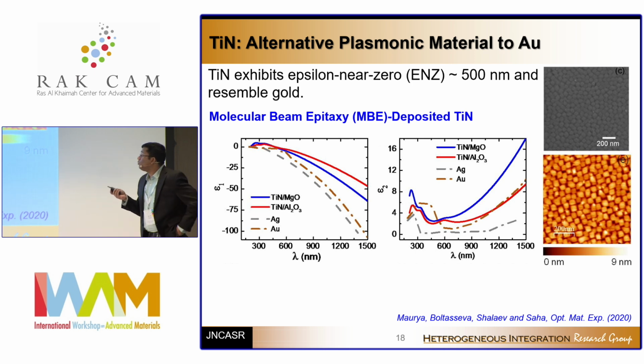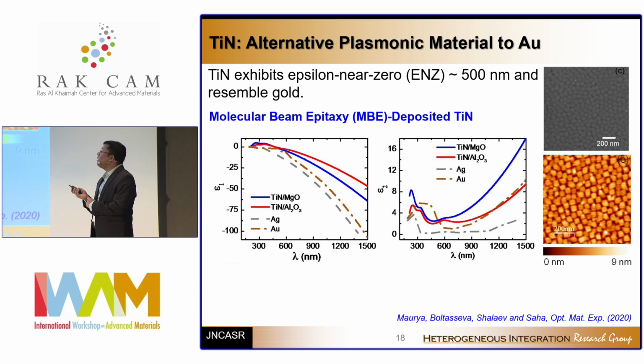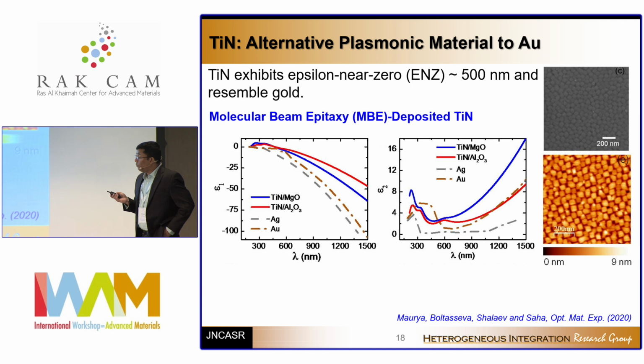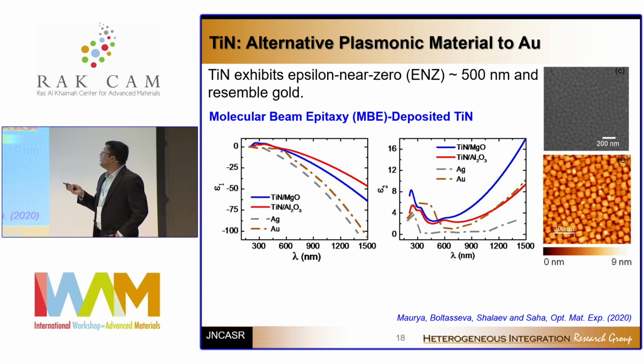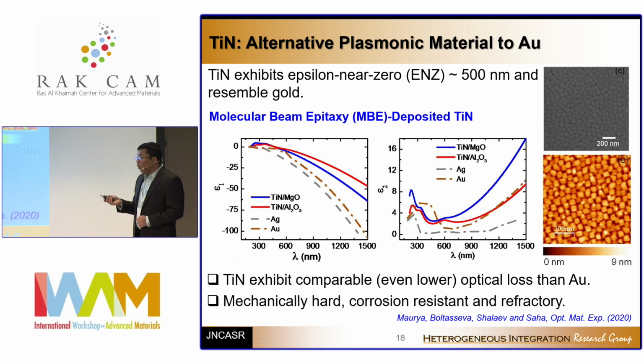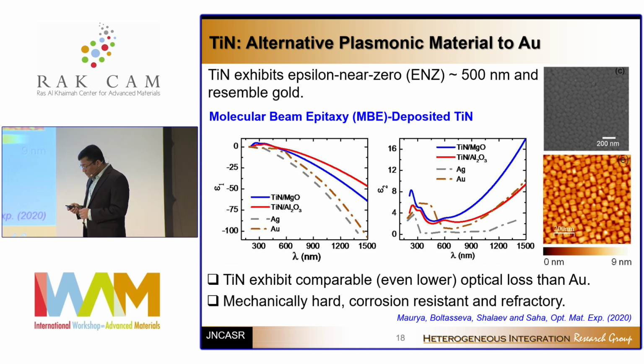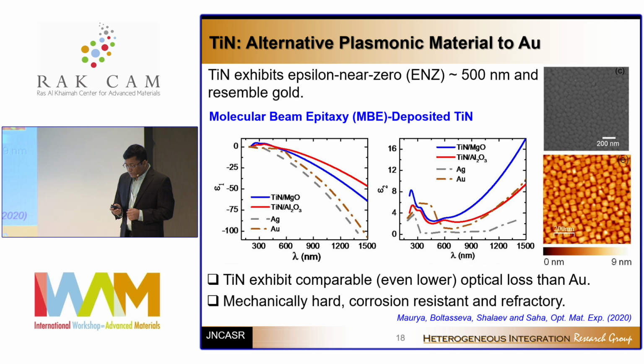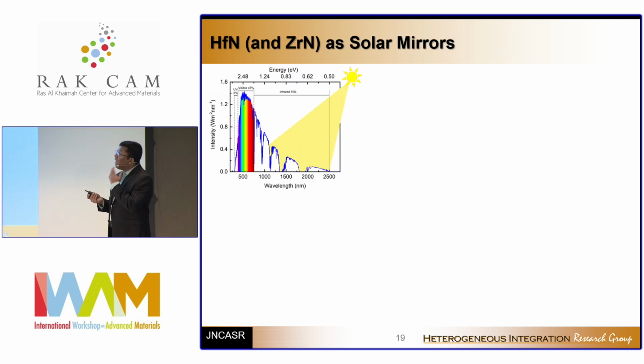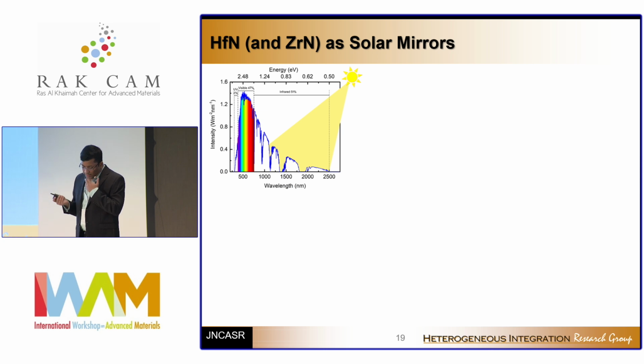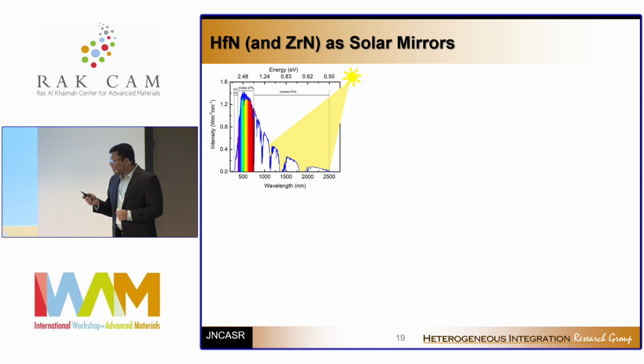One of the ways we got around this, initially when we started our independent group, is by depositing high quality epitaxial thin films of titanium nitride with molecular beam epitaxy. And when you deposit it, because you get around all the loss, all the scattering events, inelastic scattering events with defects, you can see if you focus on this red curve, the titanium nitride today has almost comparable, or in some cases lesser, optical losses compared to gold. And we have used it for many other property demonstrations also, but one real application, and I shall show it again later, is that we are trying to develop solar mirrors.